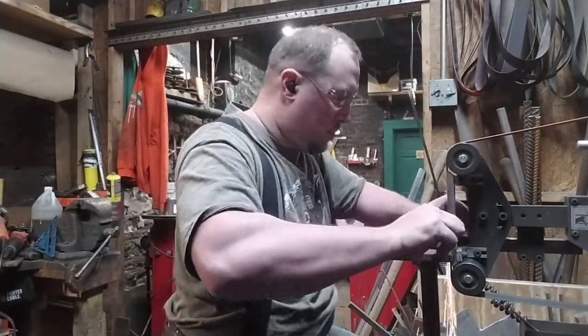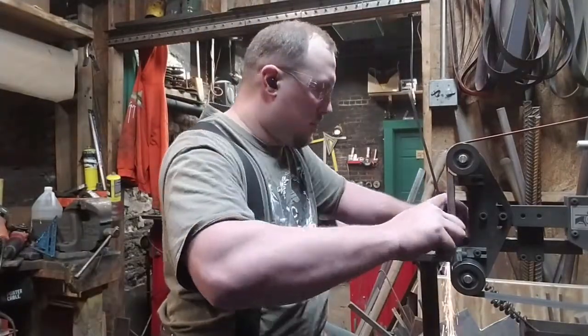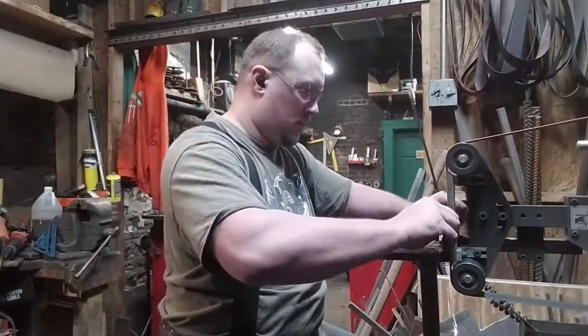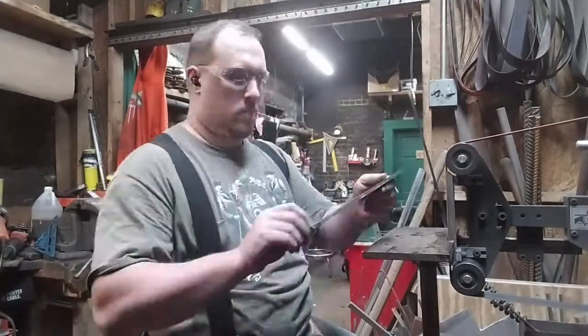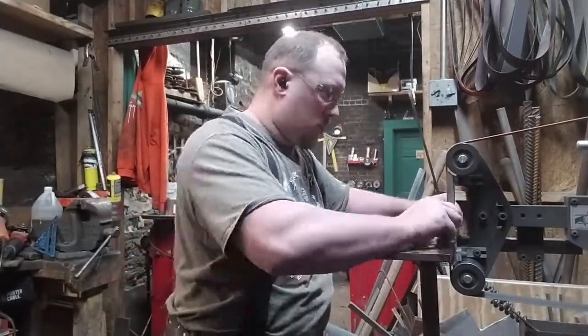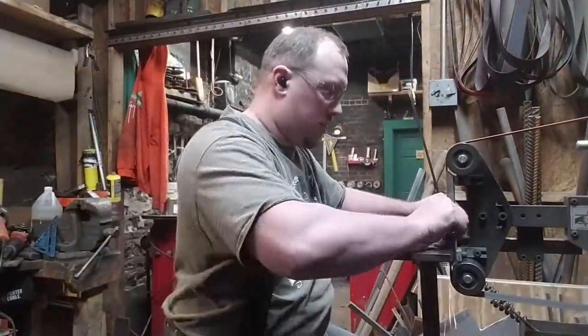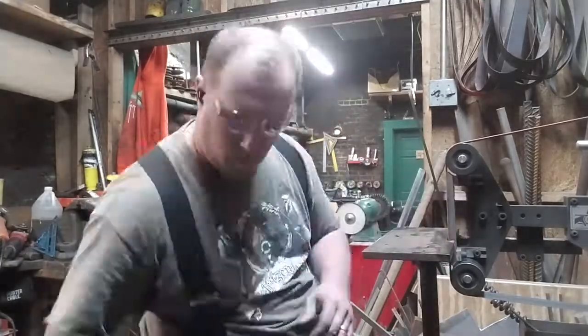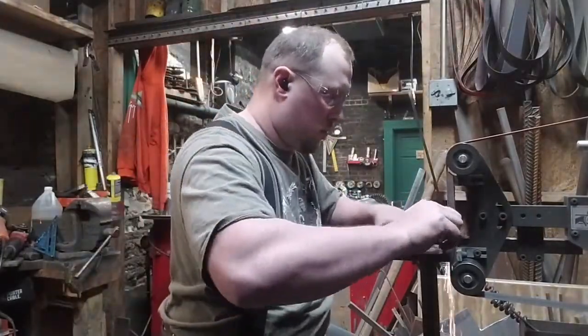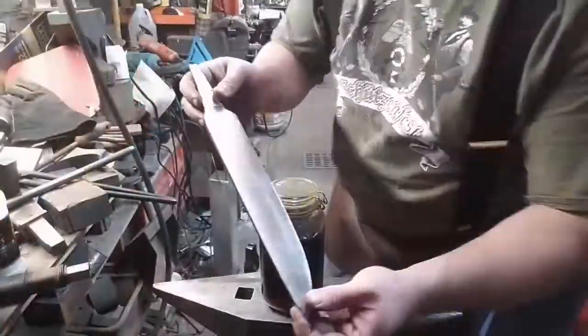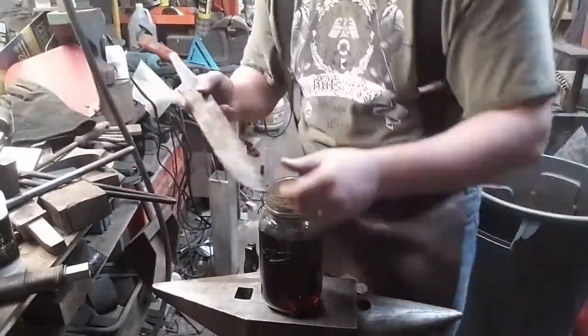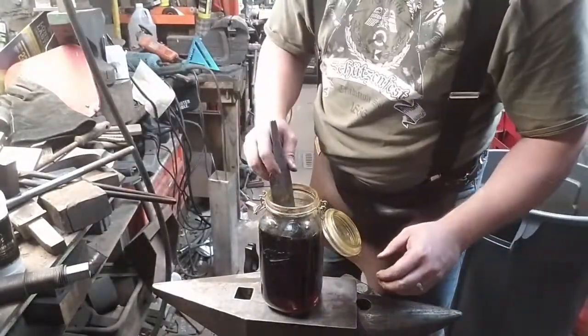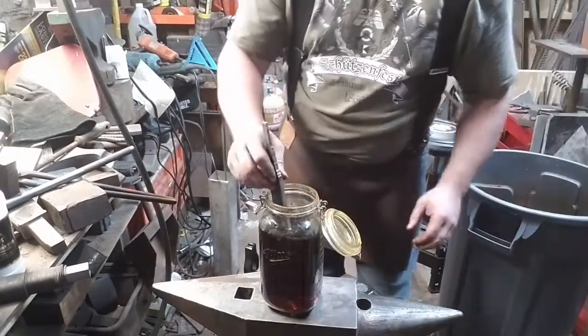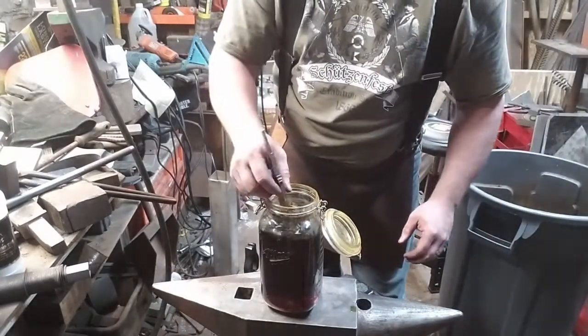We made the steel of this knife by surrounding iron bars in carbon and holding it at high temperature long enough that the carbon could soak into the iron and make steel. We made steel from iron, but the carbon can flee and make iron out of steel just as easily. Now, we've been here before with the ferric chloride, and you saw that there was no pattern on the blade, even though we know it's in there.